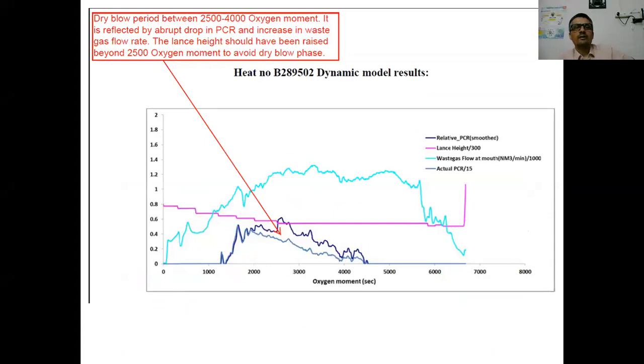So we have investigated the plant data, and based upon that, we have predicted that dry blow is occurring in this region where the post-combustion ratio is decreasing. If you look at the waste gas flow rate, there's an increase in the waste gas flow rate and a decrease in the PCR.